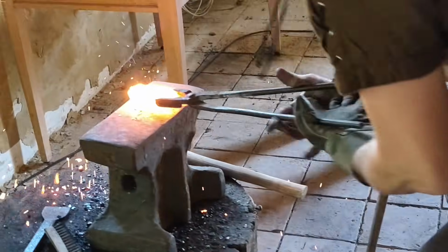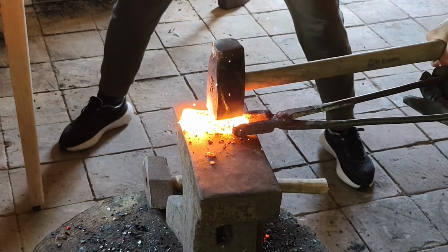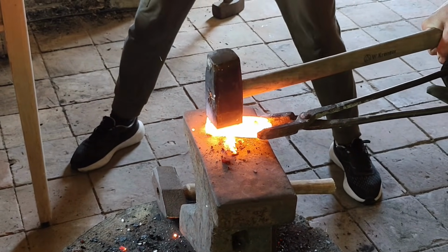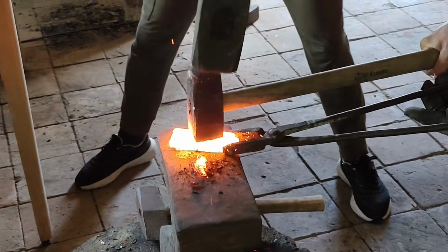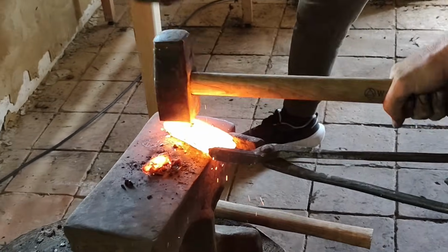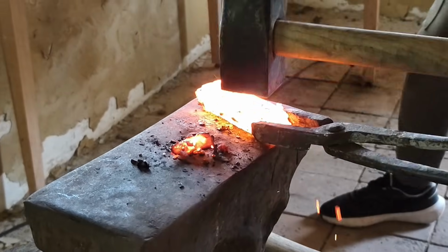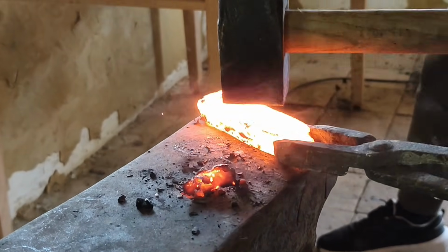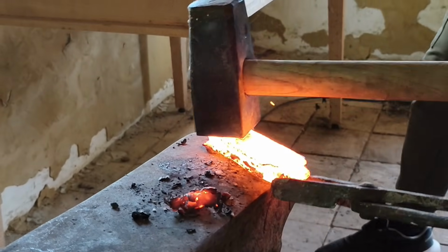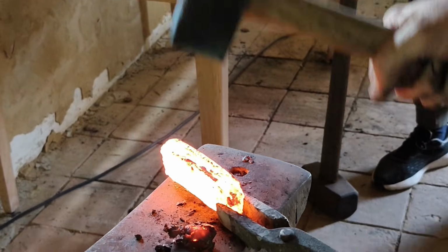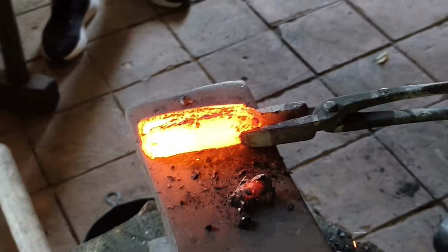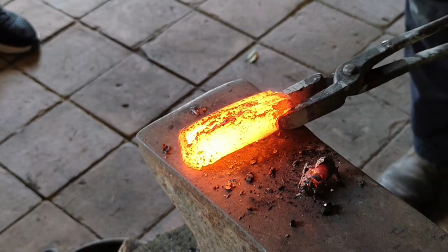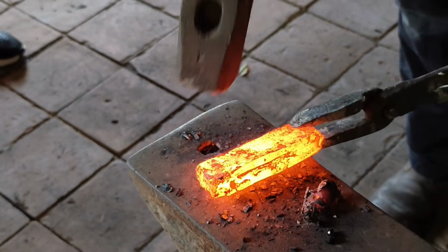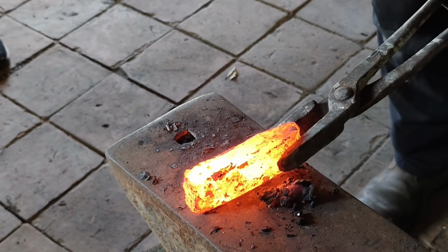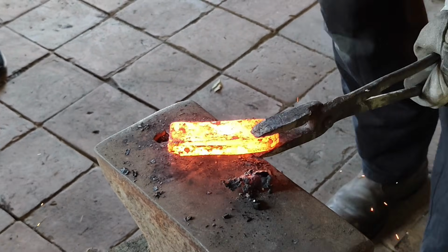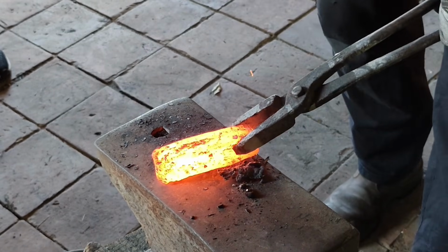Also, when constructing the sword blank from multiple smaller bars, this allows for the core billet or the interior of the sword to be made of low to medium carbon pattern welded steel. So when the fuller is then forged into the middle section of the blade, meaning that we make the middle part of the sword thinner, when the blade is subsequently quenched, the low to medium carbon core of the sword will cool fast enough, because it is made thin, to also harden. And just as importantly, it will also allow for a back temper or a spring temper to be drawn on the blade with additional heat treatment.